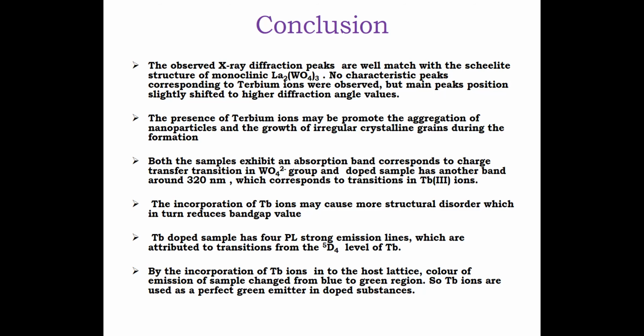And about optical studies, from UV visible absorption studies, it is clear that both the samples have an absorption band in the 240 to 260 nanometer range corresponding to oxygen to tungsten charge transfer. And the doped sample exhibits a band around 320 nanometer corresponding to the transition in terbium ions. The incorporation of terbium ions causes more structural disorder, which reduces the band gap value. The doped sample has 4 intense PL emission lines, which are attributed to the transition from the 5D4 level of the terbium ions. And the strongest emission of terbium is at 545 nanometer.